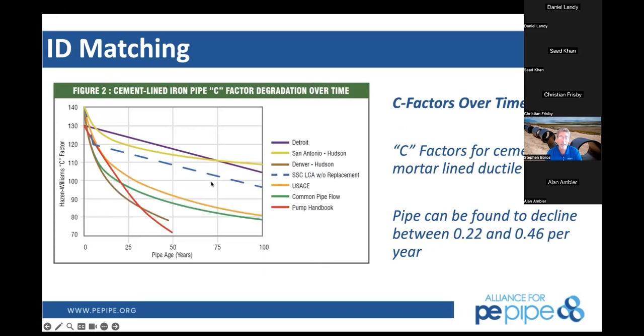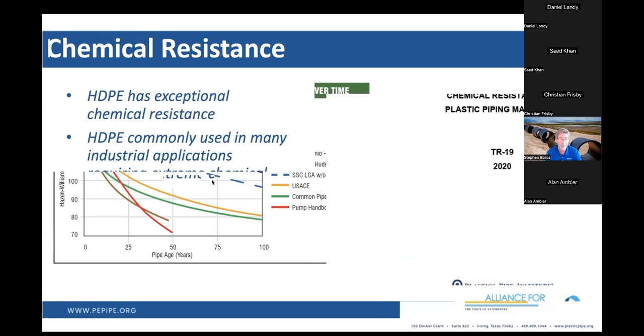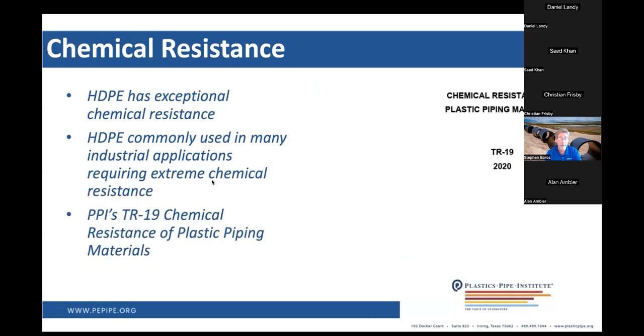If you look at other piping products, we'll just use cement lined iron pipe here for instance, everybody realizes that over time that mortar lining becomes a little more rough, it degrades, and the friction factor increases, so the corresponding C factor decreases. So depending on the age of that pipe, you're going to actually have less flow capacity, typically when you need more. I mean, these systems are put into place where you have certain needs for flow based on population and industry. And that usually doesn't go down. It usually just increases. So you want more flow over time versus less. And with polyethylene, that original C factor is never going to decrease. That's one reason why you don't need to match IDs to get equivalent flow. There's several others. That's a whole other study by itself.